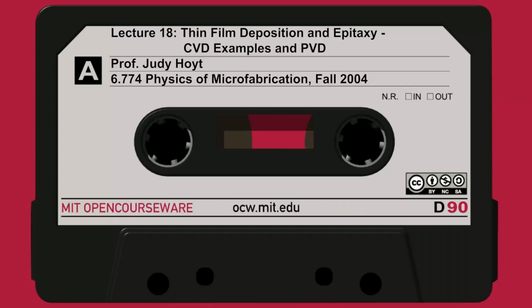This type of setup is found pretty much in every fab, maybe in a slightly different configuration, but it's essentially a hot wall furnace, and it's resistively heated. The wafers are usually put in quartz boats or quartz ware, and they usually stand up very close together. It's a batch process, so you can get 25, 50, maybe 75 wafers in a batch, quite a few wafers. You have some gas sources consisting of silane and nitrogen and maybe dopants if you want, that flow into this quartz tube, into the hot zone.